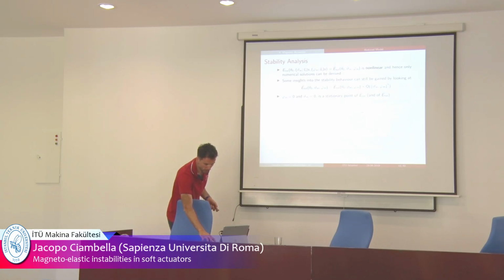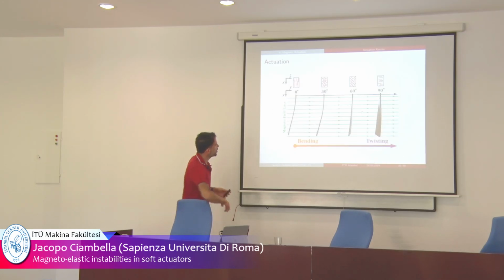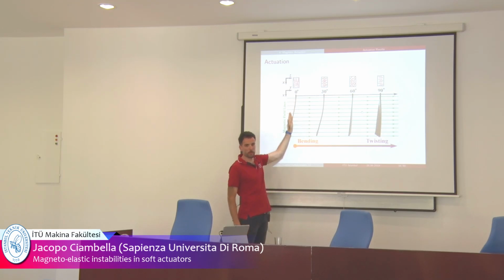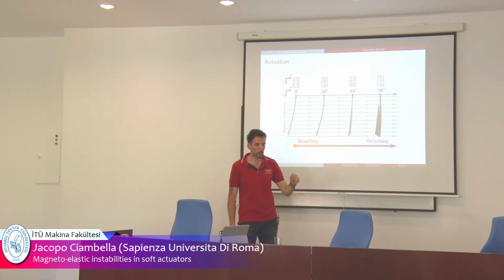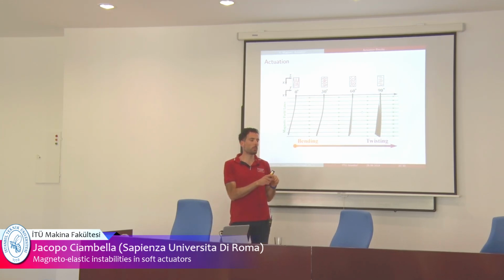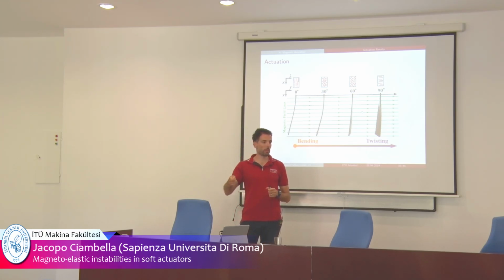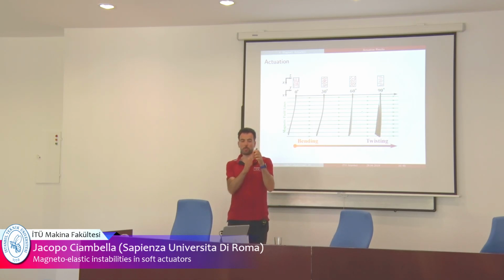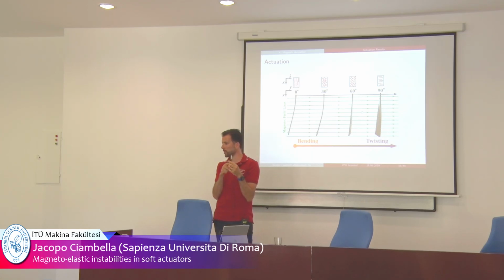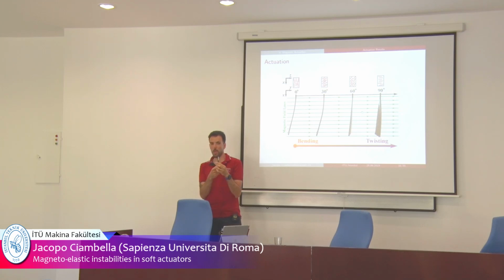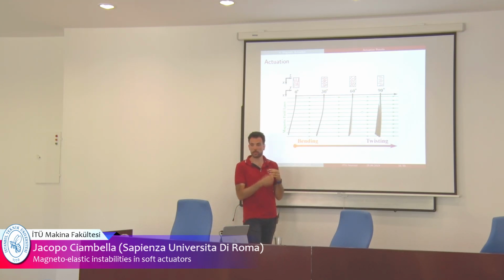And so this model explains why that was happening. Again, I'll show you here. Essentially, the fibers were initially at 0 degree. The specimen was straight, right? The field lines in that configuration are perpendicular to most of the fibers. And so if you work out the torque acting on the fibers, it is 0 in that case. When the fibers and the field are perpendicular, the torque is 0. But that's a configuration where the magnetic energy is maximum. So what we did, we started increasing the intensity of the field, increasing the magnetic energy. And because we were pumping magnetic energy into the system, the straight configuration becomes unstable, meaning that the specimen prefers to bend rather than stay straight.